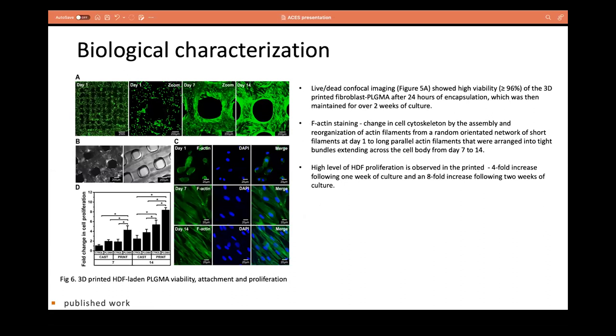Moving on to the biological characterization, the influence of the matrix on the viability, proliferation, and morphology of the printed fibroblasts was demonstrated in vitro. Here you can see the printed fibroblasts show high viability over the period of 2 weeks of culture, and high confluence of the elongated fibroblast subpopulation was observed after a week of culture, demonstrating the cells were attaching and thriving well in the matrix. This was confirmed by F-actin staining, which showed the change in cell skeleton by assembly and reorganization of the actin filaments from a randomly organized network at day one to long parallel actin filaments at day 7 to day 14. In accordance with these findings, a higher level of fibroblast proliferation was also observed in the printed fibroblast construct in figure D.